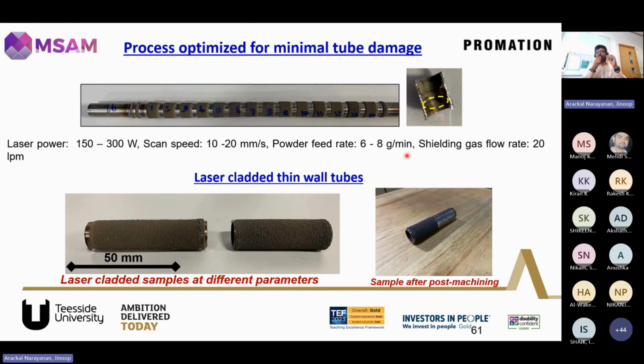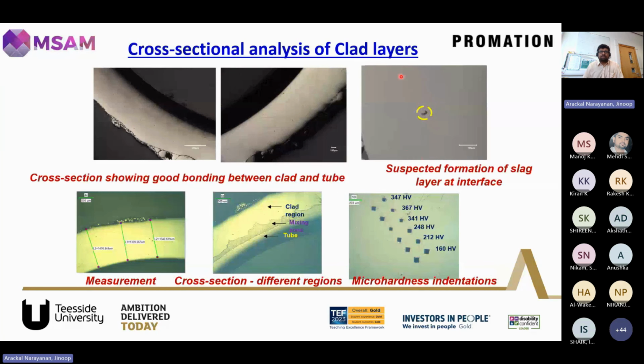So a lot of factors had to be considered in this particular case to develop a process window for this cladding. We developed this, and then we could observe very good bonding between the tube and the clad regions. And you can see how the different zones can be classified here: there's a tube region, there's a mixing zone, and the clad on top of it.